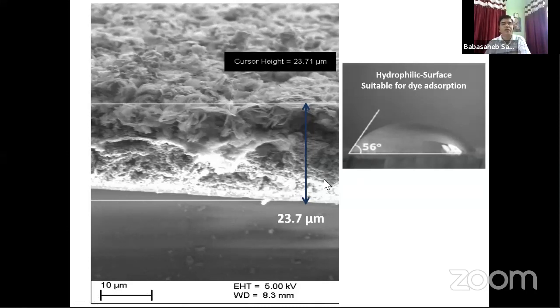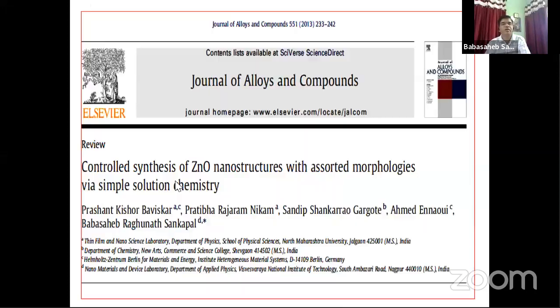All these parameters are listed in this paper, so that not only this cactus-like morphology, you can get different morphologies of the zinc oxide, maybe hexagonal, petal-like, or nanobead type morphology. All these parameters are included inside this paper, where we have used simply the CLR and CBD methods to get different morphologies of zinc oxide, with different precursors like zinc acetate, zinc nitrate, zinc chloride, zinc sulfate. Just by varying the precursor solution and the combination of CBD and CLR, you can get different morphologies of the zinc oxide by using simple solution chemistry, which can have a wide range of applications.